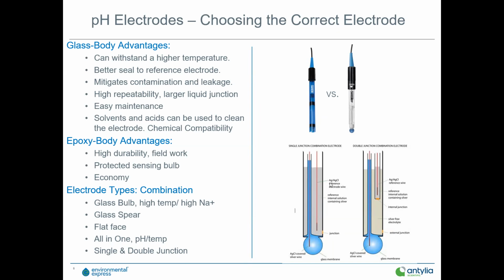The big difference here is a single junction. This is pictured kind of the lower center of this slide. As you can see, the glass bulb is what's doing the measurement. The liquid junction is where the electrolyte actually comes out into contact with your sample, as well as that glass bulb. When poisoning ions are introduced to pH electrodes, that's how they attack the electrode. They will migrate across the junction and attack this little silver chloride reference tip. That is kind of the main stability point of this single junction electrode. And when the liquid junction either dries out because it's not stored in a soaker bottle or it's not properly hydrated, that's one of the key issues you'll see.